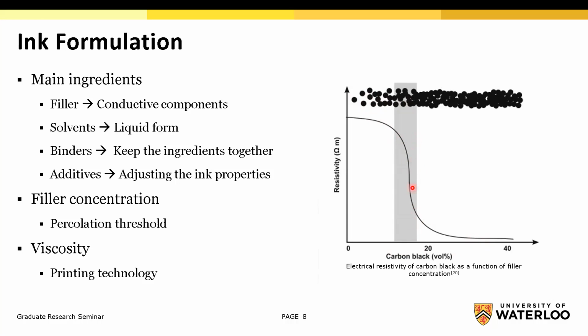So this is known as percolation threshold. You need to know the percolation threshold for an ink formulation to have a conductive ink. That depends on the geometry, size, and aspect ratio of the materials. Another aspect is viscosity. Depending on the printing technology, you need to adjust the viscosity of the ink as well.